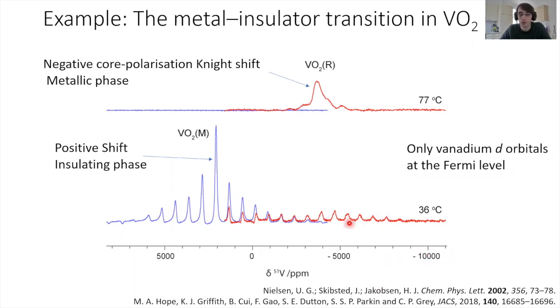This wasn't new at the time either. This has been known for many years. But this is a negative Knight shift we're observing here because there are no s orbitals at the Fermi level. The valence orbitals here are vanadium d orbitals, and so they cause core polarization of the vanadium core s orbitals, and this results in a negative Knight shift.